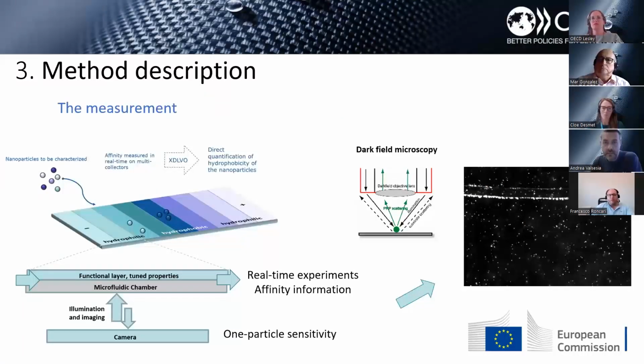The measurement, as explained before by Andrea, is based on the injection of your tested material inside the channel of the microfluidic cell mounted on the collector. Then you put your collector under the microscope and make the focus, and you are able to measure in real time the affinity of your particles for the collector, with a sensitivity of one particle, thanks to the dark-field microscopy technique. The output of your measurement is an image sequence of 25 frames, which you can see on the right of the screen. Next, please.